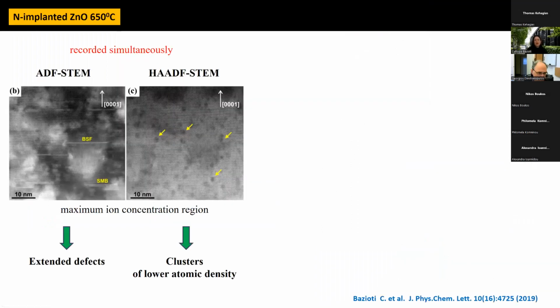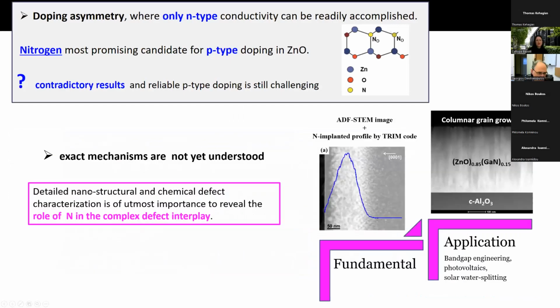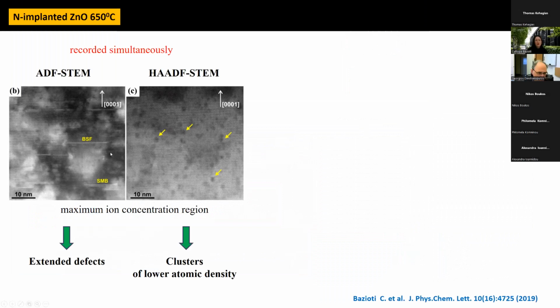Now, I start with the fundamental study that we did in nitrogen-implanted zinc oxide after annealing. Here you can see two images recorded simultaneously in medium magnification, and you can already understand the importance of the complementarity of using different detectors for imaging. For example, in annular dark field, due to the intense diffraction contrast, we can easily see the localization of extended defects. While with high-angle annular dark field imaging, due to the Z contrast, we can easily see the localization of clusters of lower atomic density.